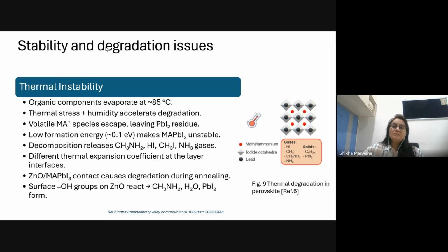So first is the thermal instability. By this I mean that generally, before you take any material into account for commercialization, it undergoes certain tests. One of the tests that we carry out is 85% relative humidity and 85 degrees Celsius temperature. We expose the material to that much environmental stress, and then see how it behaves.